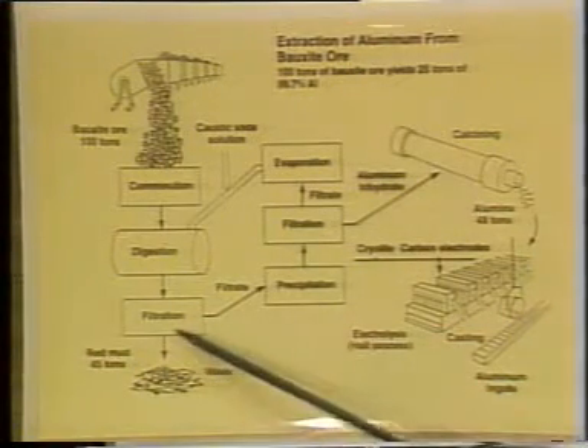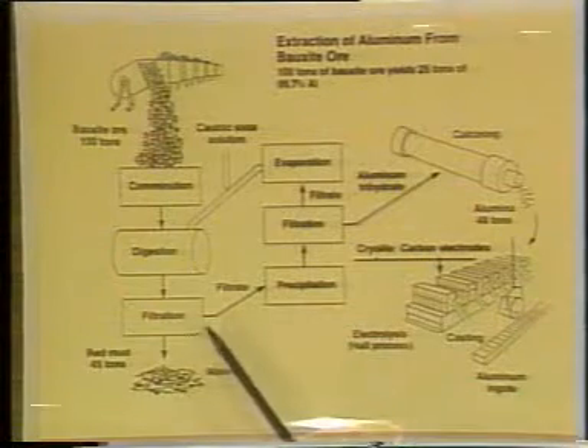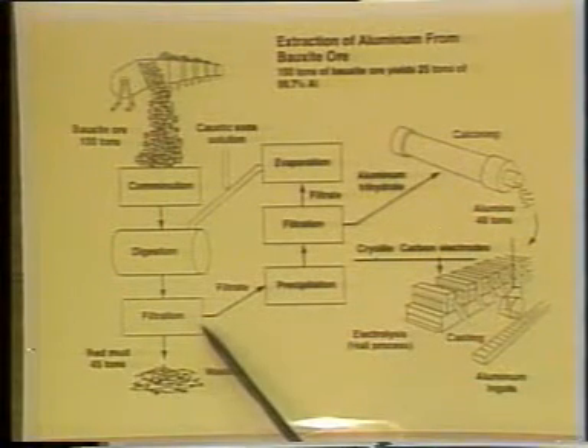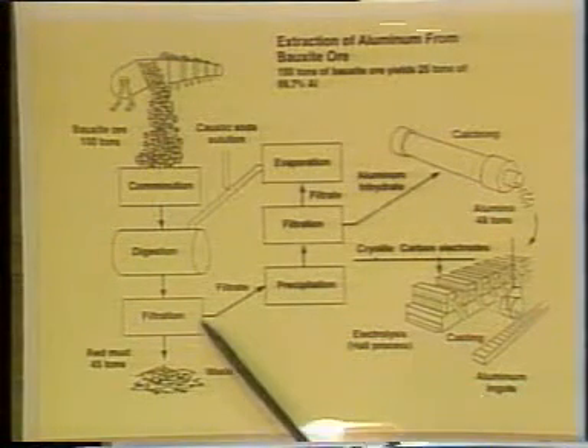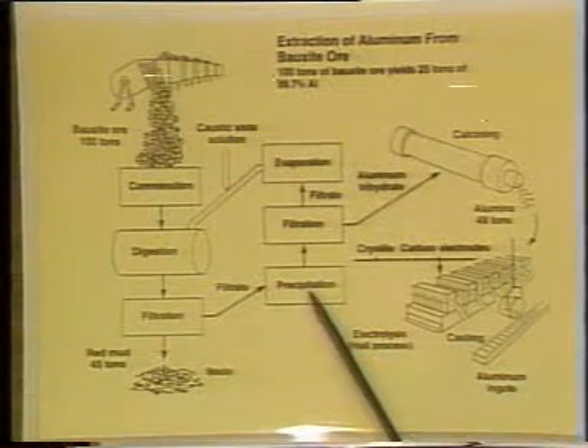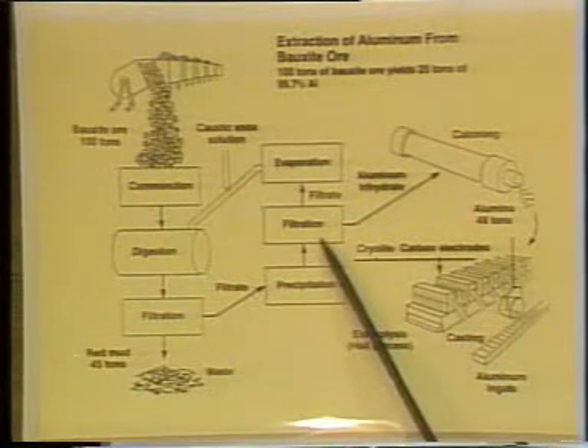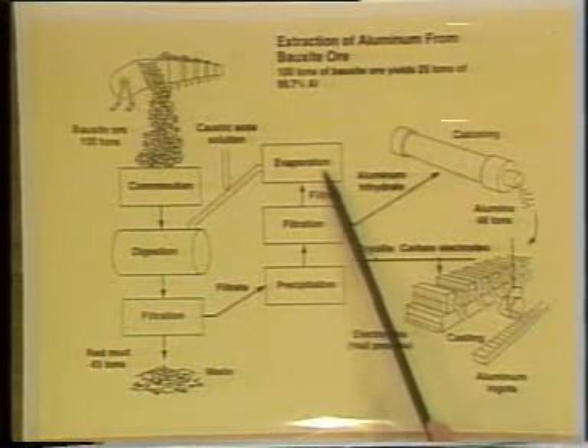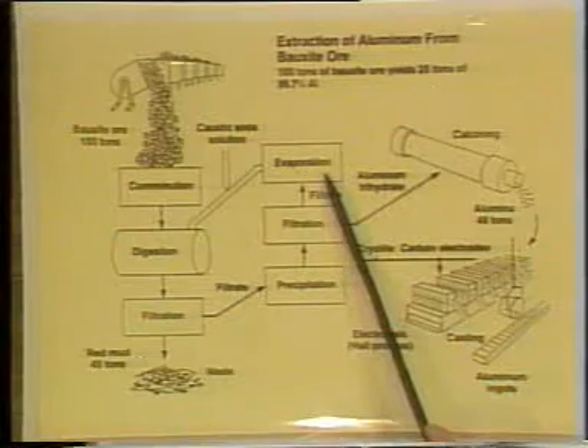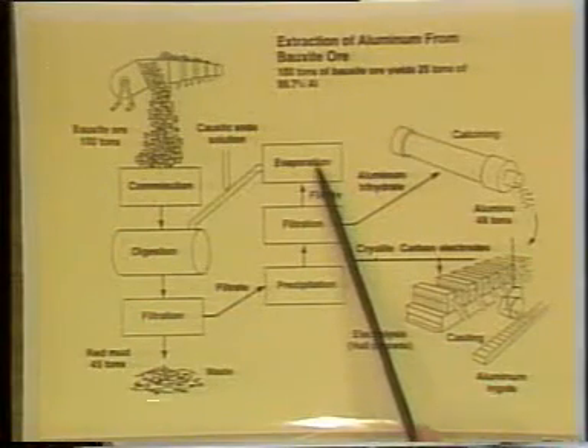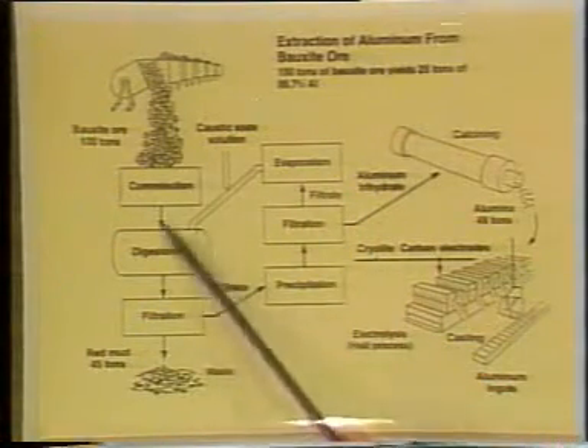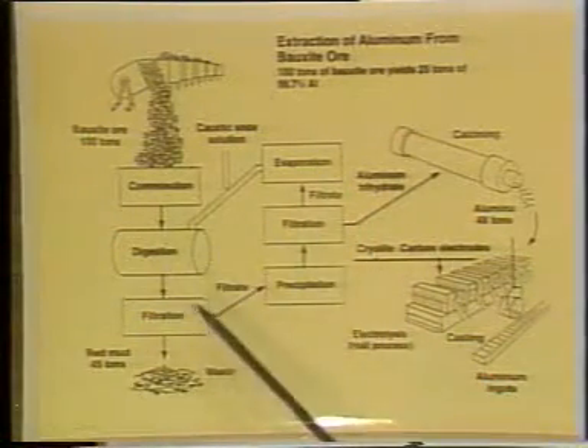Having filtered it out, now we have to precipitate that particular aluminum oxide from the solution, and we do that in a precipitation tank. And we have to filter the material, and then we evaporate off the sodium hydroxide solutions, and they're carried back to the digester, and this continues to go on over and over and over.